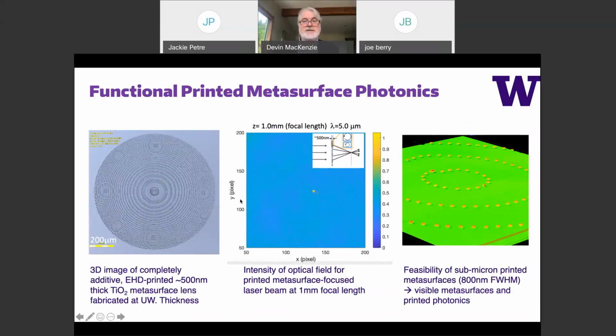An example of a printed metasurface using different phase shifts is the lensing part, which is a total of about 500 nanometers thick, and it can have a focal length as short as 10, 15 microns, but certainly millimeter focal length. This lens, 500 nanometers, focuses a 5 micron laser, ultra flat. So you think about ultra flat solar micro concentrators, things like that. It's very, very interesting.